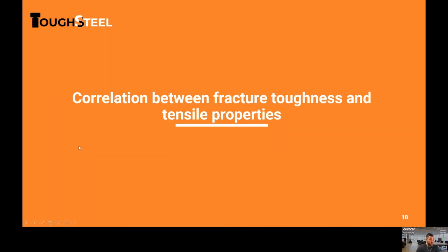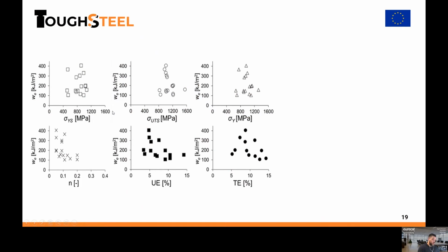Now I wanted to illustrate, because I said at the beginning that one important message is that fracture toughness cannot be estimated from tensile properties. Here we illustrate the correlation between the essential work of fracture, on the y-axis, and different tensile properties: yield strength, tensile strength, the average of yield strength and tensile strength, sigma y, strain hardening, or elongation values. As we can see, there is no correlation between this crack propagation resistance and conventional tensile properties. So the common way of thinking, that higher uniform elongation, total elongation, or higher strain hardening means a higher fracture toughness, we can see is not true.